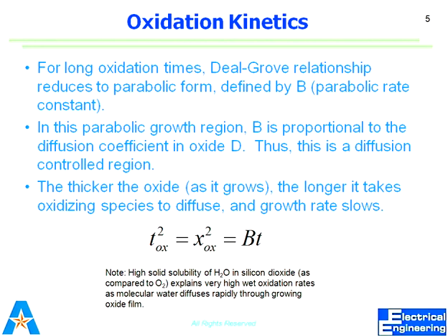So now you got the answer to your question, that when it gets thick, there should be some problem. So now you come to know it is telling you, yes, there is a problem. In this region, due to the thick oxide layer, the diffusion does not permit all the gas molecules to diffuse through, because it will offer some resistance. It will be reluctant to letting all the gas molecules diffuse through it. So that's why very few of the gas molecules reach the surface, and whatever reaches, that is getting reacted, because there are more silicon molecules as compared to whatever is reaching when the thick oxide layer comes into play. Any confusion about both these regions? What is the difference between linear and parabolic?